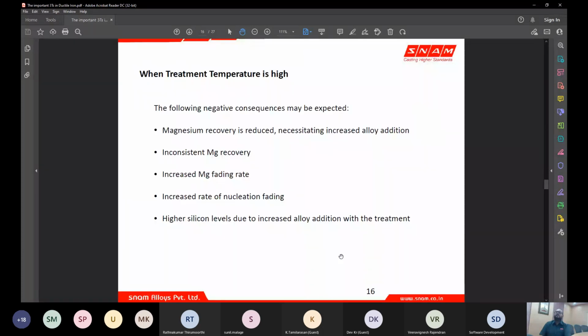And when the treatment or tapping temperature is very high, your magnesium recovery is going to decrease, and it can lead to inconsistent or increased alloy addition. Your magnesium recovery can become inconsistent. Your magnesium fading rate can increase because you start boiling the magnesium for a longer time. The rate of nucleation fading can increase, and because of all these things, you need to add more silicon. Because of this, you might end up with higher silicon because of the increase in addition rates, or you might have to control this by having a lower silicon in your base metal.